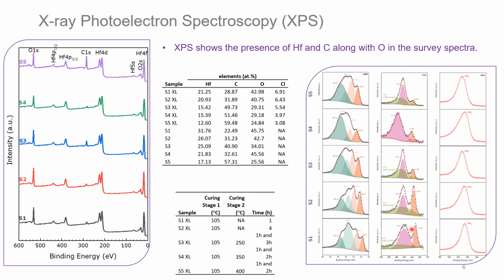This figure shows here the high-resolution hafnium, carbon, and oxygen spectra and the chemical bonding states of these elements. The hafnium profile showed the presence of hafnium carbide peaks for hafnium 4f doublet. Hafnium oxide peaks were also observed for all the samples. The carbon spectra also showed the presence of hafnium carbide bonds along with the presence of free carbon in the ceramic structure. For oxygen spectra, the peak was assigned to the oxygen atoms in hafnium.